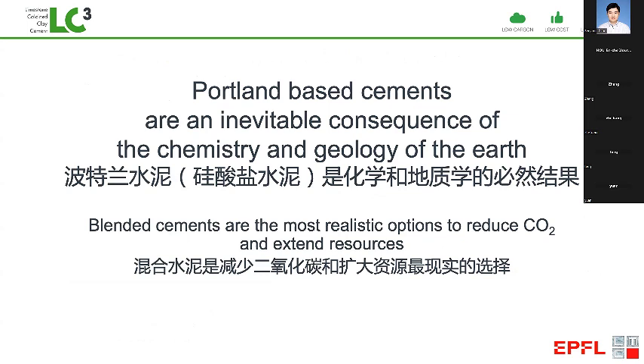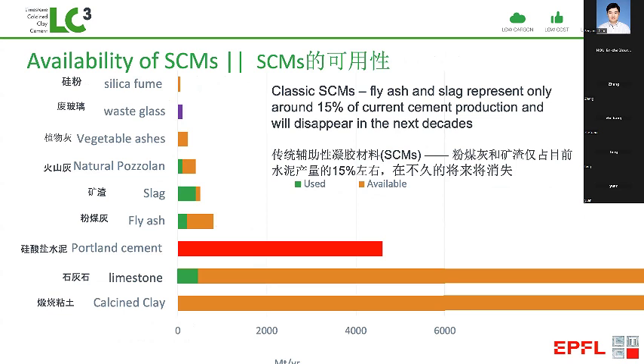And also this is important because blended cements have already been used for many decades. For many decades, we have cements which are incorporating slag, which comes from producing iron, and fly ash, which comes from coal. However, today, the amount of slag and fly ash available worldwide is only about 15% of the demand for cement. And this amount will decrease in the future because the most important thing we have to do to avoid global warming is to stop burning coal. So fly ash in medium term will disappear, slag amounts will decrease.